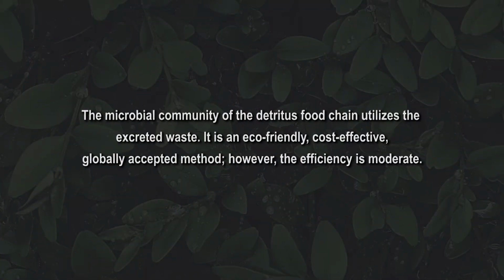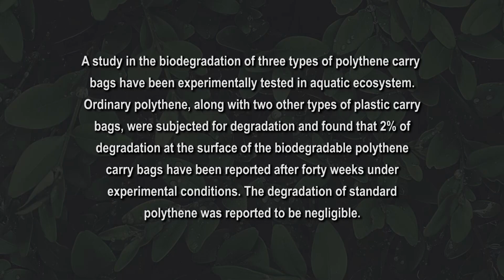The microbial community of the detritus food chain utilizes the excreted waste. It is an eco-friendly, cost-effective, globally accepted method. However, the efficiency is moderate. A study on the biodegradation of 3 types of polythene carry bags has been experimentally tested in an aquatic ecosystem. Ordinary polythene along with 2 other types of plastic carry bags were subjected to degradation, and 2% degradation at the surface of the biodegradable polythene carry bags was reported after 40 weeks under experimental conditions. The degradation of standard polythene was reported to be negligible.